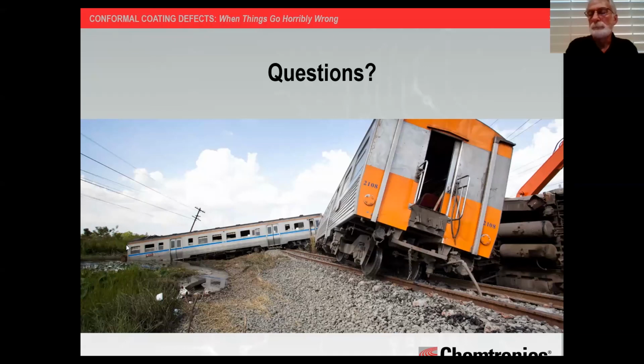I have a question. We've got just a few minutes. You brought up surface tension a couple of times, Pierce. And so the question is, if you're having a surface tension issue, is there a way to test the surface tension of your board and compare it to what it should be, or what the surface tension of the material is? You can actually, a laboratory can test the surface tension of, say, the coating liquid. There's dynamic and then there's static surface tension testing.